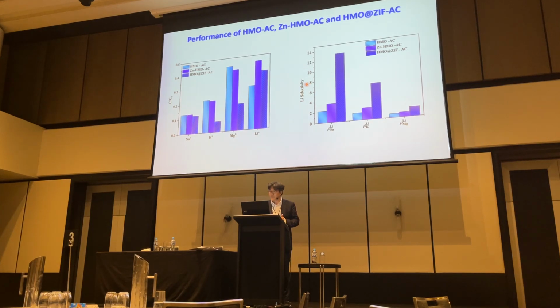So we look at those selectivities, compared to the HMO and zinc HMO. We found the selectivity is around 13 for this HMO-ZIF activated carbon with the sodium, and then potassium is around 6, and then magnesium is around 2. Higher selectivity we achieved from this HMO and ZIF material.